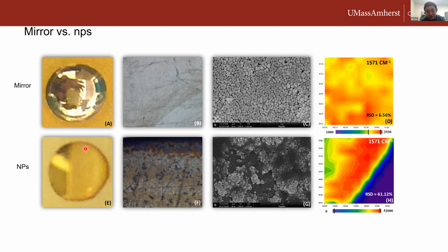If we look at the image on the top, image A is the wet mirror when it's not dried, so it's pretty shiny, so that we call it a mirror. Then if we look at image C, this is also the SEM image of that mirror. You can see all of those silver nanoparticles are very aggregated, but they are also evenly distributed. If we look at the very right, this is the same compound we detected. Using the silver mirror, we have a very good signal recovery, and the signal is very uniform all across the board. Whereas if we look down, that is the coffee ring method. We only have a high signal recovery on the rings, but outside of the ring or inside of the droplet, you won't have a very good signal recovery.